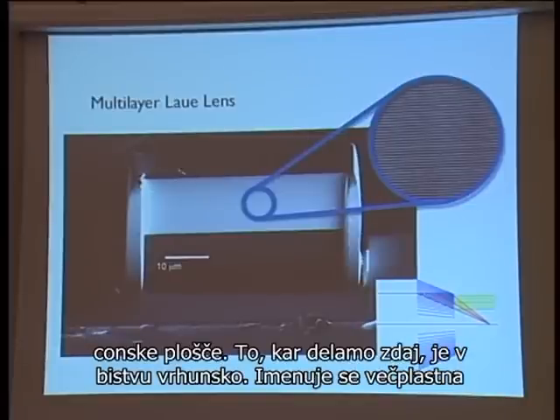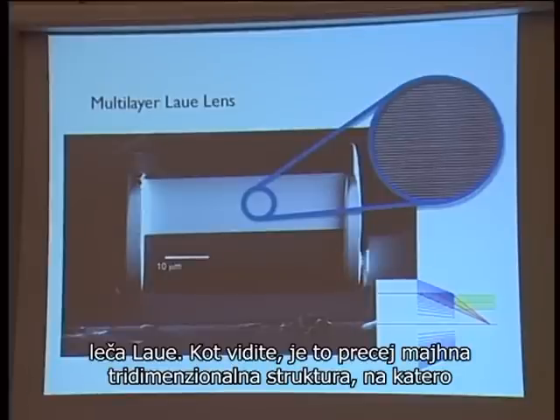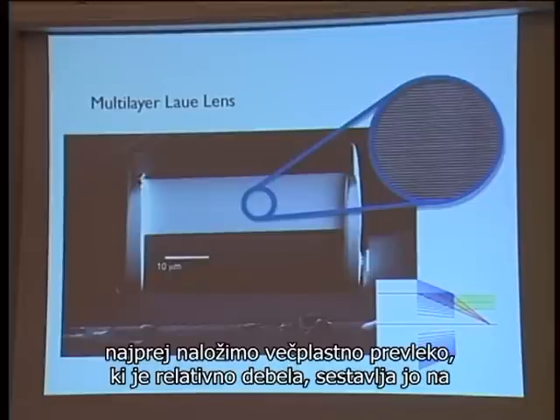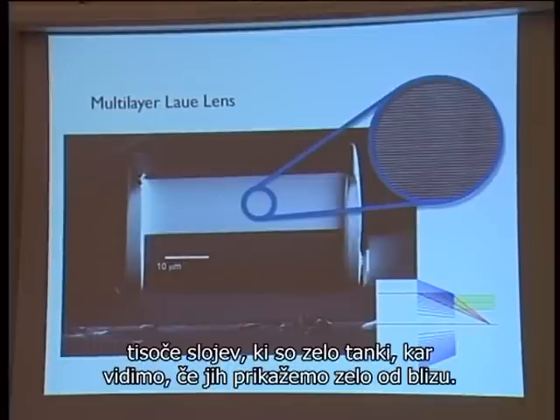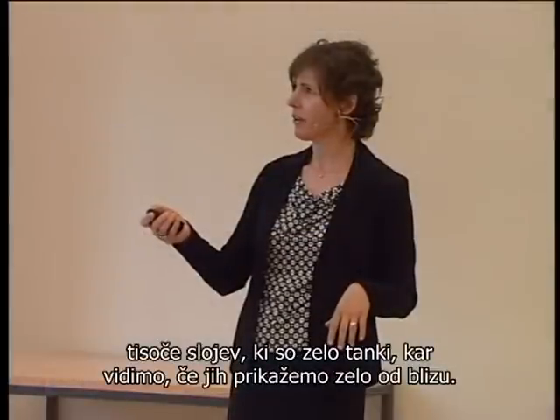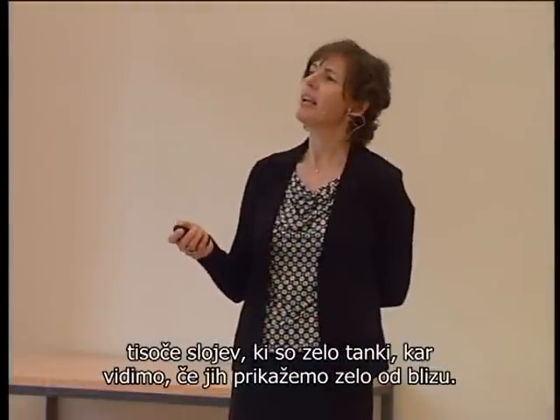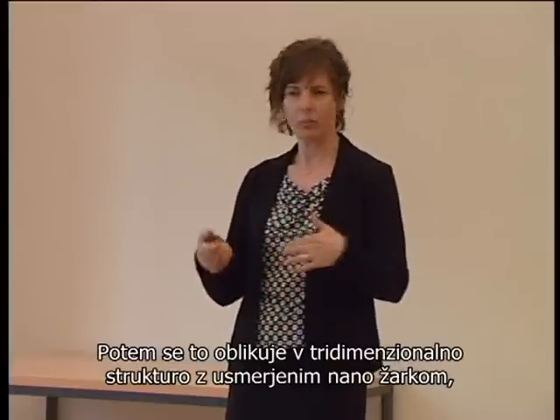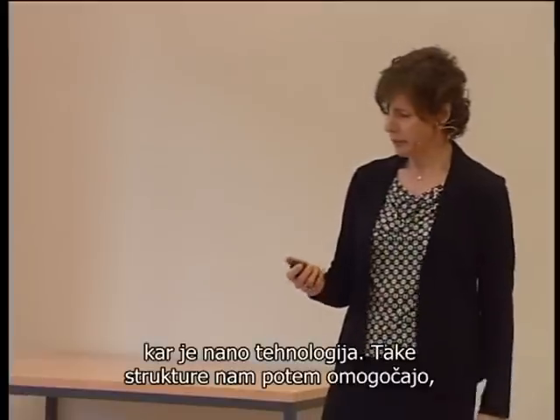It's called a multilayer Laue lens. It's a three-dimensional structure, rather small as you can see, where we first deposited a multilayer that's rather thick overall, consisting of thousands of layers, which are, as you see, very thin if we zoom in, and then shaped in the third dimension with focused ion beam, which is a nanotechnology tool.